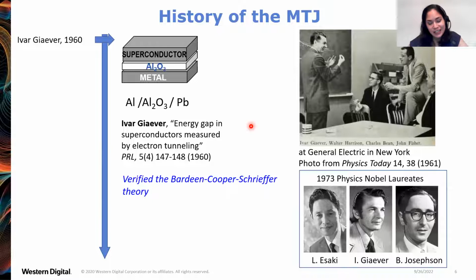Ivar Giaever was trained as a mechanical engineer, but he found himself among physicists and started taking physics classes at the local college. And they just started getting onto the superconductivity chapter. So he had the idea of putting a superconducting lead counter electrode here to form this tri-layer tunnel junction. And with this tunnel junction, he showed the energy gap in the superconductor measured by electron tunneling from the aluminum into the lead superconductor. And this was a remarkable verification of the BCS theory. And for this, he was awarded the Nobel Prize in Physics in 1973.